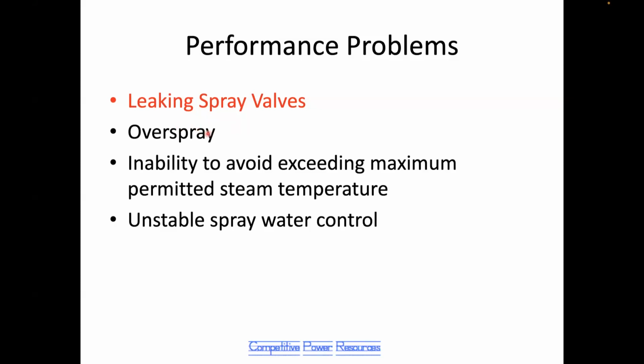Once you've cooled the steam to 25 C above saturation temperature, if you cool it any more than 25 C superheat, we consider that overspray. You're getting too close to saturation and you probably are doing damage in the pipework. Some units are not able to spray enough water during startup to avoid exceeding the maximum permitted steam temperature limit at the outlet of the superheater. Again, how to deal with that is beyond our scope today, but some units have that issue.